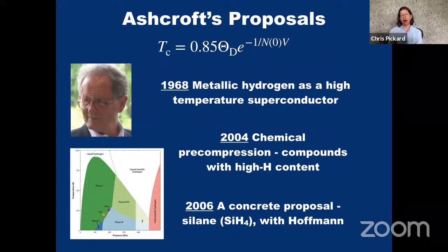So Neil Ashcroft's argument was that if you take the very simple expression for the superconducting transition temperature at the top, which is proportional to the Debye temperature multiplied by an exponential depending on the density of states at the Fermi level and the electron-phonon coupling strength, then if you could get a very high Debye temperature, your TC should go up. And so where could you get a high Debye temperature? Well, from hydrogen, it's very light. It has high frequency vibrations. And so that was really the essence of the argument.